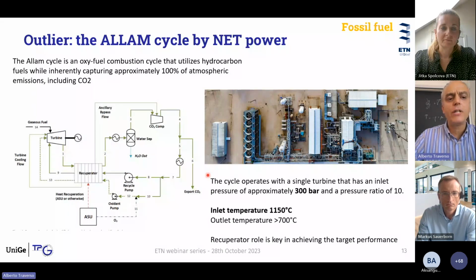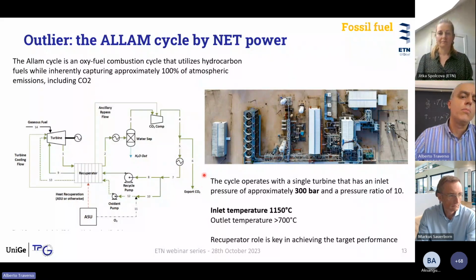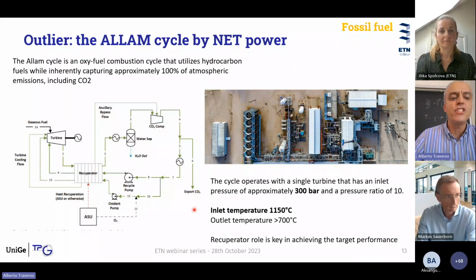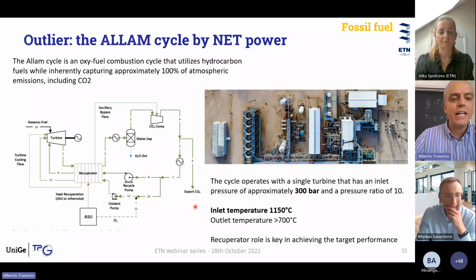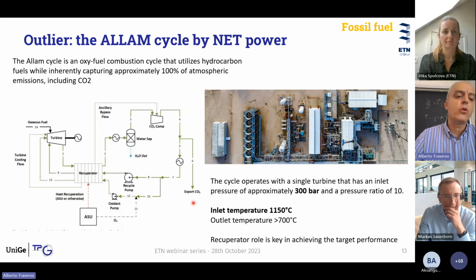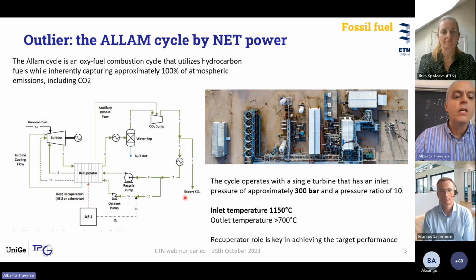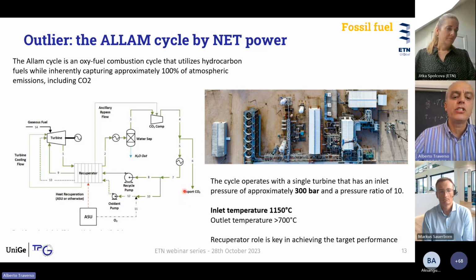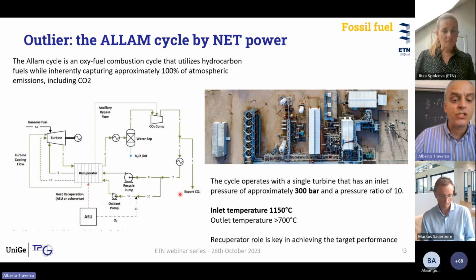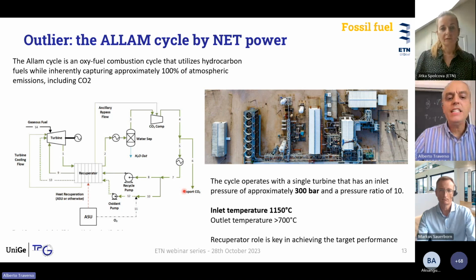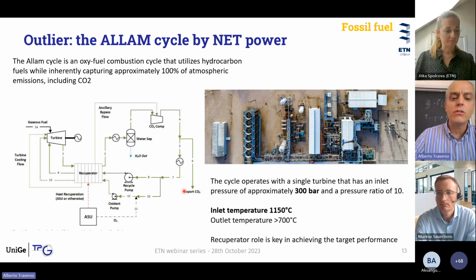I said I wanted to mention an outlier turbine. This is the only oxy-combustion case I mentioned, for this cycle, also called the NET Power cycle or Allam cycle. The conditions to operate the turbine are particularly demanding. In fact, the system targets power production from fossil fuel with parallel CO2 separation and export at pressure to some reservoir. In this case, we see that the design condition for the turbine is 300 bar with an expansion ratio of about 10.